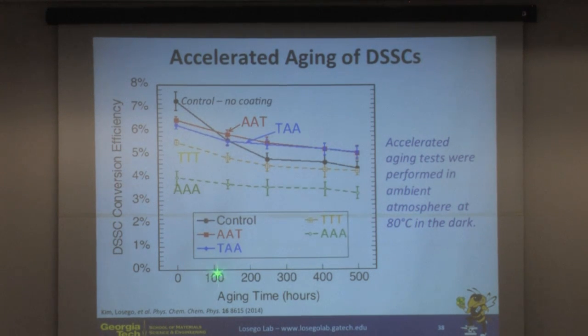And so we see after about 100 hours, our devices are equivalent to our control devices, and beyond that, they show higher efficiency than the control. So the control has degraded at a faster rate and ends up being lower performing than our coated devices.